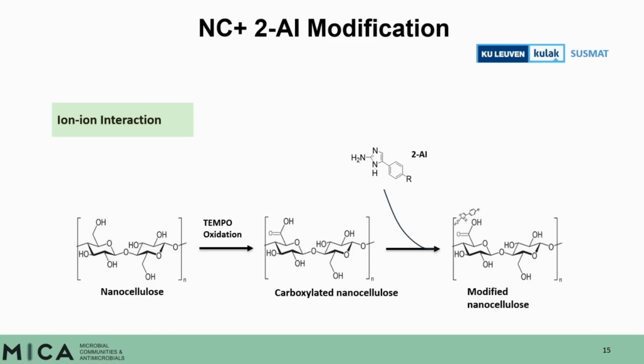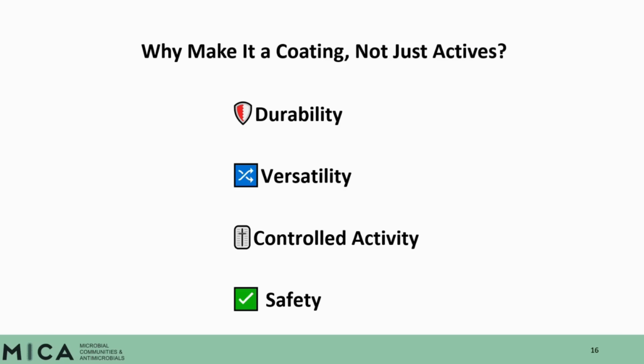For the modification of the nanocellulose with the 2AI, nanocellulose first undergoes TEMPO oxidation to form carboxylated nanocellulose, and then the negatively charged carboxyl group of the carboxylated nanocellulose interacts with the positively charged amino group of the 2AI to form the modified nanocellulose by ionic interaction.